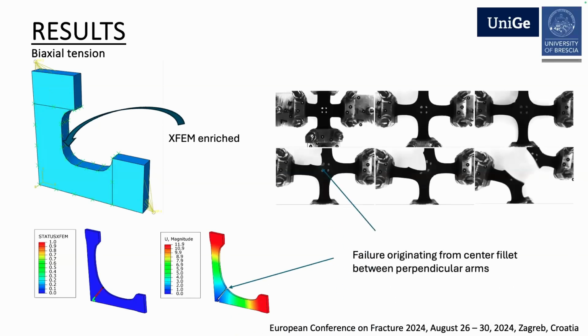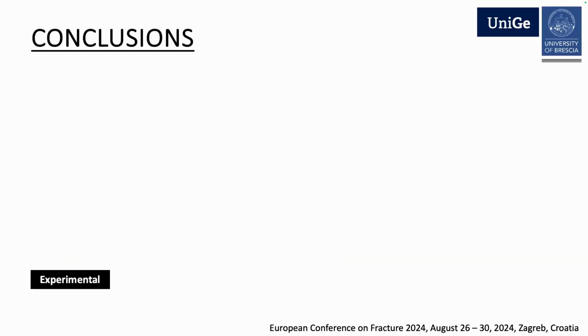And finally, I would say the next step is to enrich this model with XFEM, trying to reproduce the failure that we observed experimentally, where actually in the biaxial test, we have the propagation of a crack from the fillet that is usually present at the connection between the perpendicular arms of the cruciform specimen. So the final goal is actually to use this type of characterization, this type of constitutive law, in a more complex model of the whole composite material structure, in which, as I mentioned before, we have used up to now a hyperelastic law.